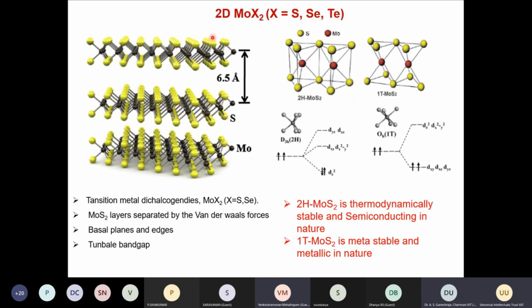So molybdenum sulfide is a very interesting material. It has a layer structure. If you see, the molybdenum and the yellow colors are the sulfur atoms. The distance between these two layers is roughly 6.5 angstroms in the bulk. What is very interesting is that the interaction between them is through weak van der Waals interaction. One can actually tune these layer structures very effectively.